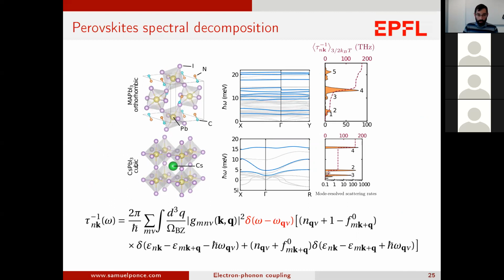The difference being that this is cubic. Here you can look at the phonon band structure of MAPI, and this is the phonon band structure of cubic cesium lead iodide. You can see that this has soft modes. And here in blue, I've highlighted the modes that contribute most to the electron-phonon coupling.